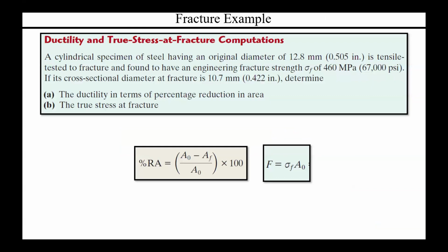So let's do an example again. This is a problem where you have a cylindrical rod, its original diameter, and it is tensile tested to fracture. So that means we did a tensile test and it ultimately failed. Well, the material failed, not the test failed. And we know that it has an engineering fracture strength of 460 megapascals, and we know what its cross-sectional diameter was at fracture. And there's two things you need to do. The first is figure out what the ductility is in terms of the percent reduction in area, and the second is the true stress at fracture. So you'll take a minute to do these on your own.